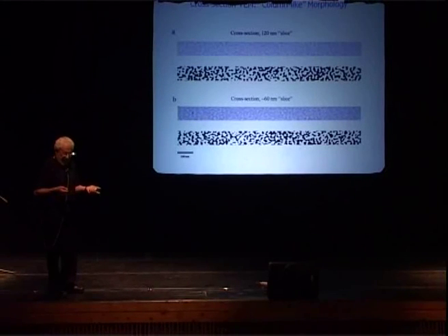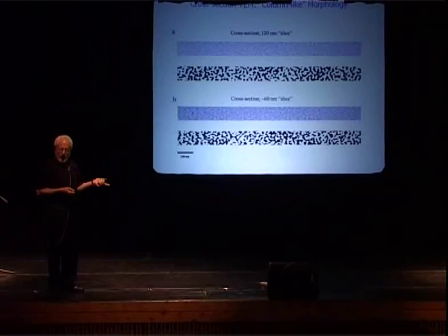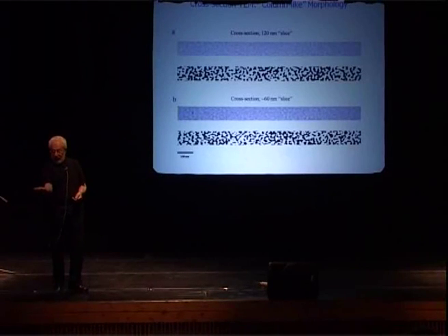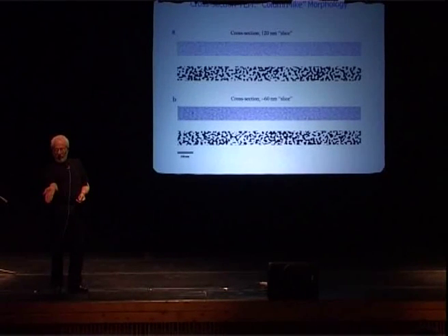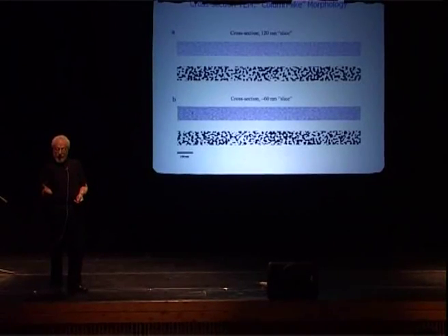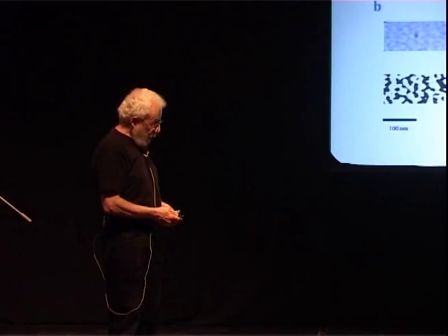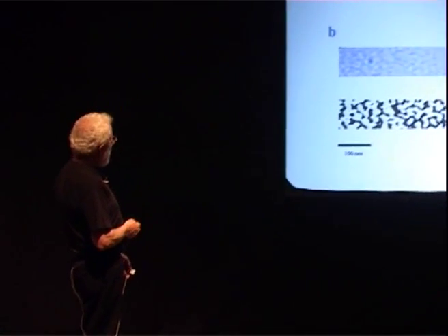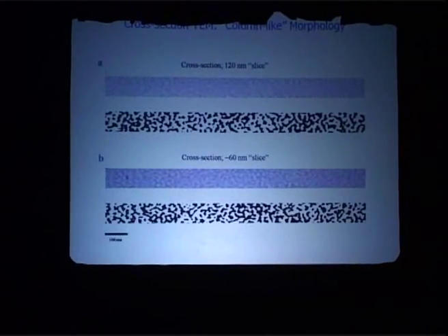The way you would find out, and we're trying to do that, is by doing tomography, reconstructing a three-dimensional image and cutting it digitally. How do you do that? You take a film and you first tilt it this way, and then you tilt it this way, and then you've got the information to reconstruct the three-dimensional image, and then you can do tomography. People are starting to do this. I hope one day to be able to show you a set of images showing that this point, or a point like this, does come to the electrode. I don't have that data. I'm inferring that, because, as I said, one infers high connectivity from the actual results.